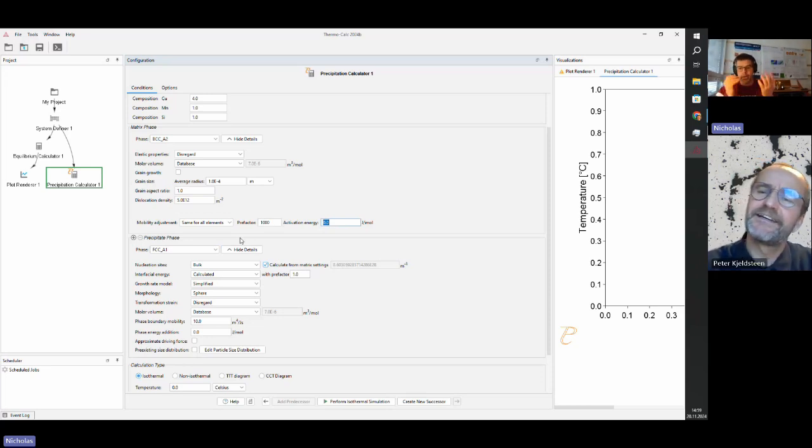But there is some logic in this. If you cool this down to low temperatures, it'll be stressed, there'll be dislocations in there, and these form fast diffusion paths. So this is actually quite standard, that you have to enhance mobility at low temperatures. Also, grain boundary diffusion becomes more important at low temperatures, and so on. So that's the first thing I'd like to do.